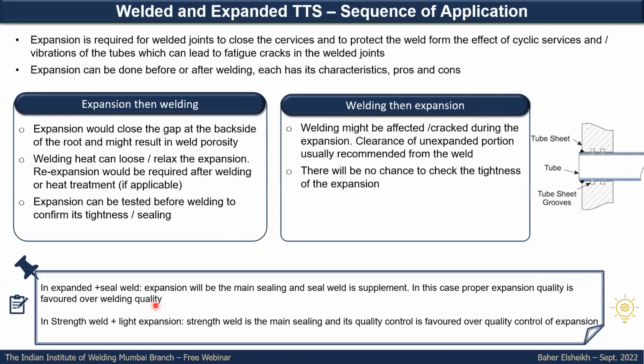One aspect you might need to think about is expanded and seal welded joints. In an expanded and seal welded joint, the main sealing is the expansion, and the seal weld is the supplement. It means you need to think about how to maintain your main seal in higher quality. So if you are thinking about compromising one of them, in this case you need to think about maintaining the expansion rather than maintaining the seal weld. Yes, definitely you have to maintain both, but this is just a point to think about. The expansion here is the main seal.